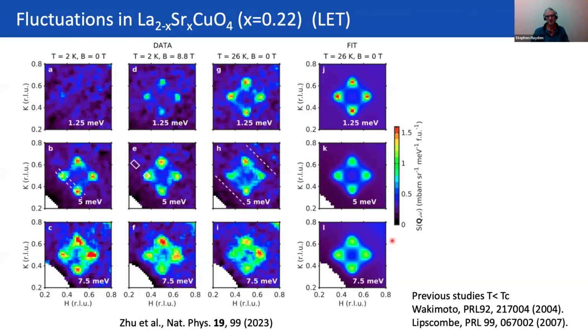Now let's go to our new data on the overdoped side, and here we have this data on LET. We can go down to very low energies, and here you see data taken for different temperatures and fields. This is the data taken in the normal state, and you can see these 4 peaks in the response very well developed here at an energy of about 1.2 meV, and then as you go up, things broaden out and it starts to get a little bit weaker.